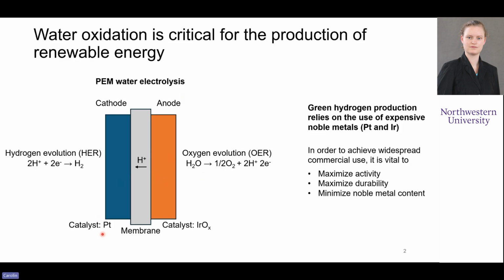And so as you can see from the setup, both sides, the cathode and the anode, require really expensive noble metal catalysts. Cathode catalysts are typically platinum-based, while anode catalysts are iridium oxide. And iridium is one of the rarest elements on Earth, and it's the key driver for water electrolyzer cost. And so in order to achieve widespread commercial use of this technology, we need to maximize catalyst activity, maximize its durability, and also minimize the noble metal content to drive the cost down. So I'll talk a bit about these anode reactions and the iridium oxide materials that are used to split water into oxygen and protons.